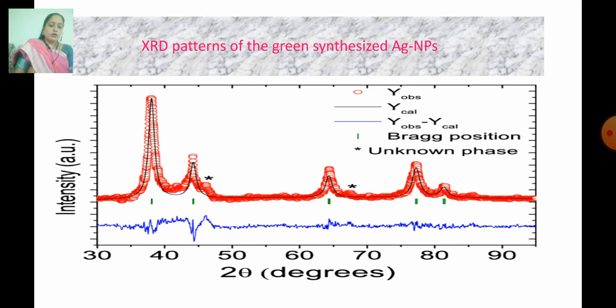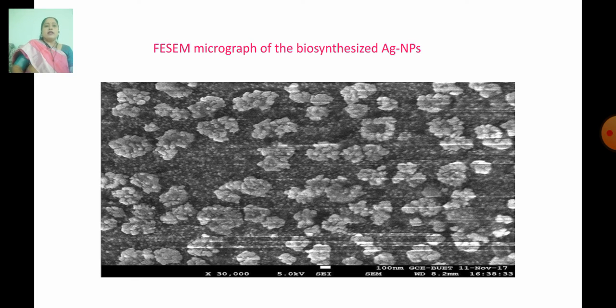We want to confirm the crystalline nature of these silver nanoparticles, so we use the XRD technique here. We get such a graph, and the diffraction peaks at the 2 theta values show that it is a face centered cubic crystal. We can determine the crystalline size using this XRD technique. Similarly, for the biosynthesis of these silver nanoparticles, the surface morphology of the particles can be monitored using the field emission scanning electron microscope method, and in this way we get such a picture.